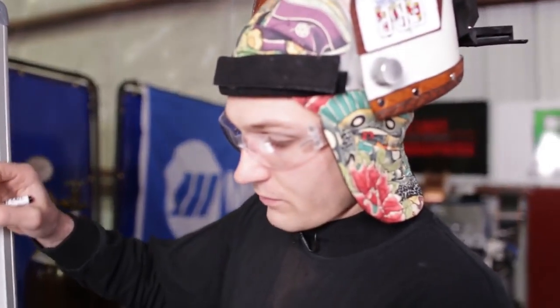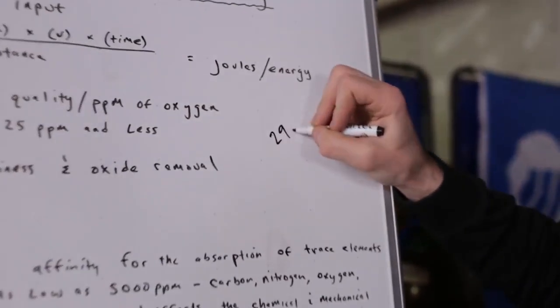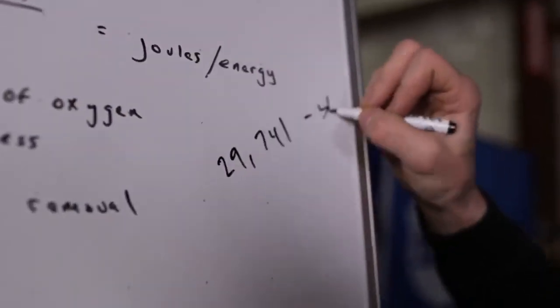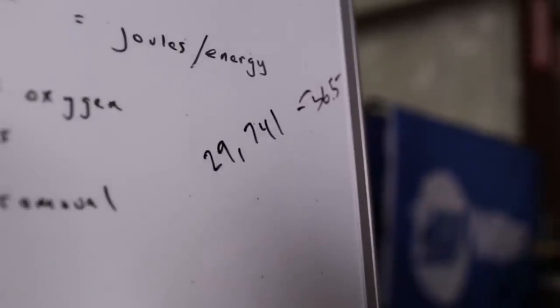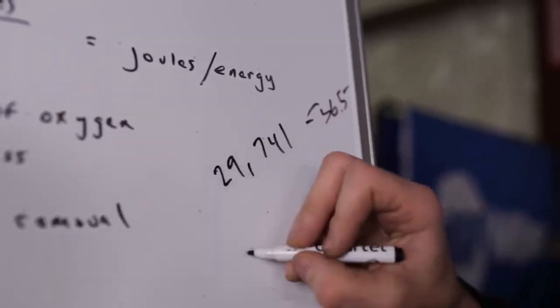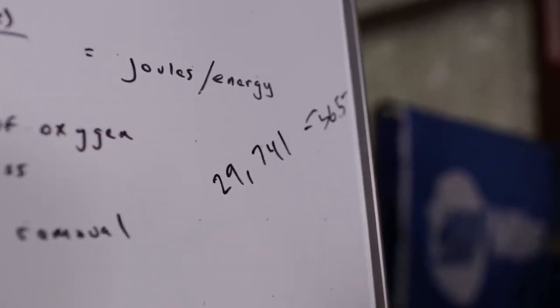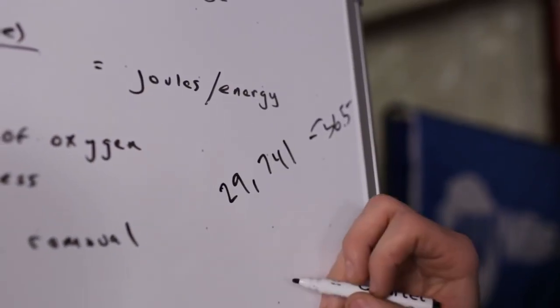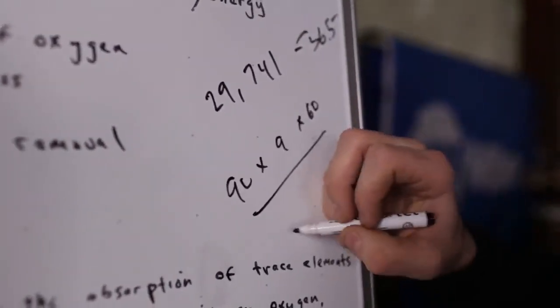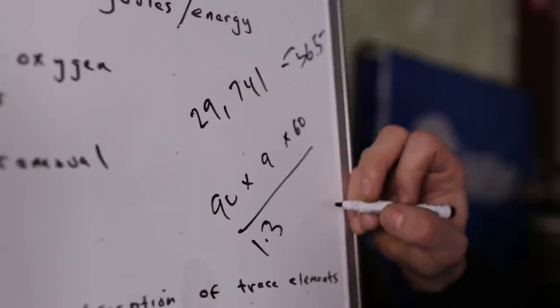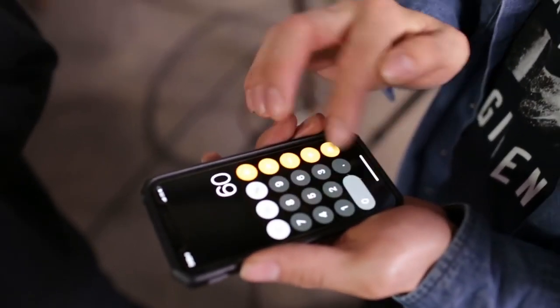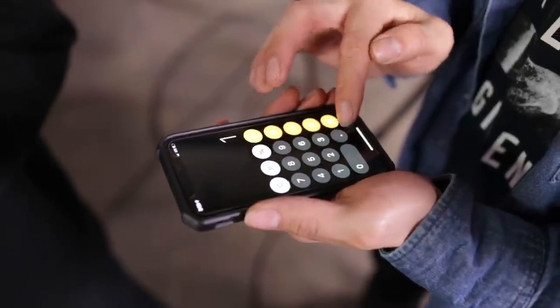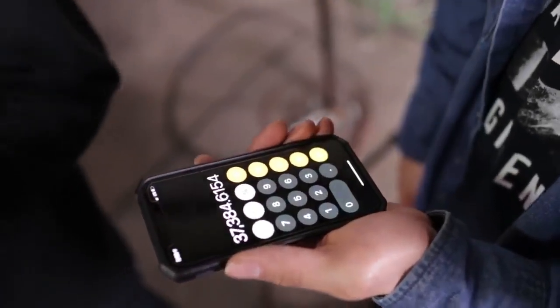For example, say a welding procedure for super duplex allows a root pass of 29,741 to 36,5 joules. On the 1/8 root pass, it's allowable from 70 to 200 amps, a voltage range of 8 to 12, and 1.3 to 14 inches per minute. Say we have 90 amps times 9 volts times 60 seconds, divided by 1.3 inches per minute. That gives us 37,384.